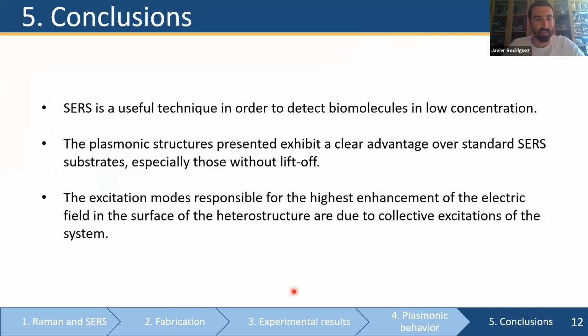So finally, just to wrap everything up, we have seen that SERS is a useful technique to detect biomolecules in really low concentration, and even by simple methods. We have also shown that the plasmonic structures presented here have clear advantages over standard SERS substrates, and more specifically, those structures without the liftoff are outperforming the structures with the liftoff. And finally, the excitation modes that are responsible for this high enhancement of the electric field in the surface of the structure are due to collective excitations of the system. So this connects with what we were looking for and what Amilcar was explaining before. And we can also add that these collective excitations are strongly related with diffraction conditions of each structure.